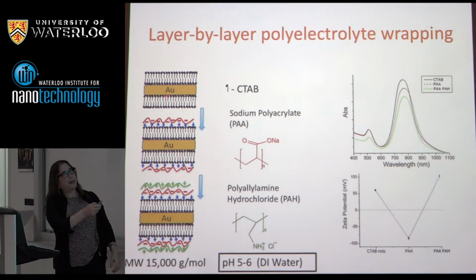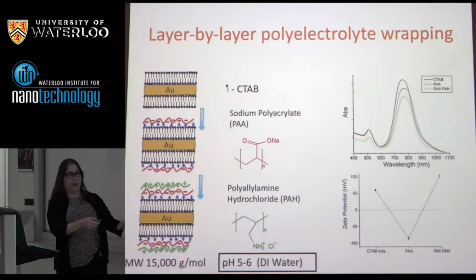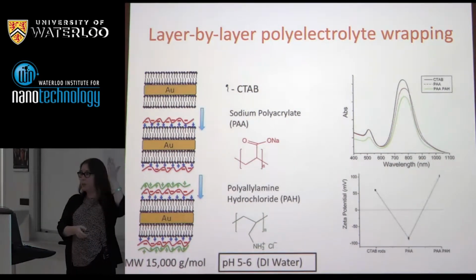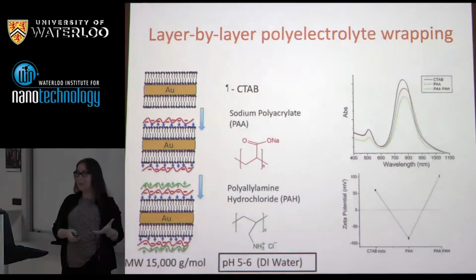So here are the particles that I start with. I can buy this polymer, sodium polyacrylate, PAA. It's got a net negative charge at the right pH. And you can incubate these two together, wait a while, and spin out the particles and resuspend them. They were cationic. Now they're anionic. You come in with a positively charged polymer like this one down here, at the right pH. You wait a while with the right ionic strength, et cetera, right molecular weight polymers here. And then you can separate the particles, and then you go cationic. So you can flip the surface charge between layers pretty significantly.